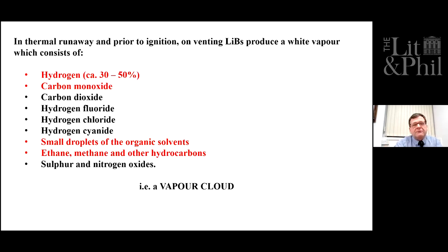Now, prior to ignition, the gases that are produced will eventually vent. In prismatic and cylindrical cells, because they are in metal cans, they vent through blast caps, safety valves. With pouch cells, the pouch cells simply burst. And what's emitted is hydrogen up to 50%, carbon monoxide, carbon dioxide, and a series of very toxic gases, hydrogen fluoride, hydrogen chloride, and hydrogen cyanide. Gases such as ethane, methane, and other hydrocarbons, and also small droplets of the organic solvent. And this gives it a thick white appearance, which has been mistaken for smoke and also for steam. But it is, in fact, a vapor cloud.